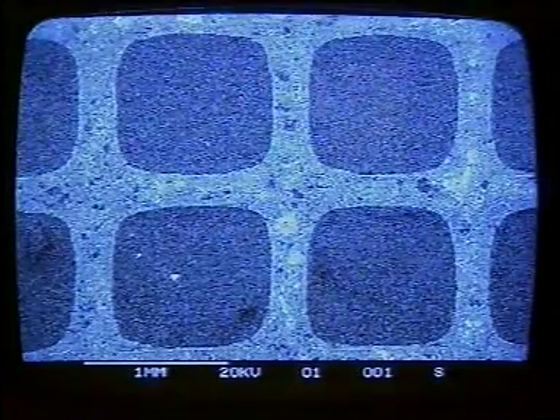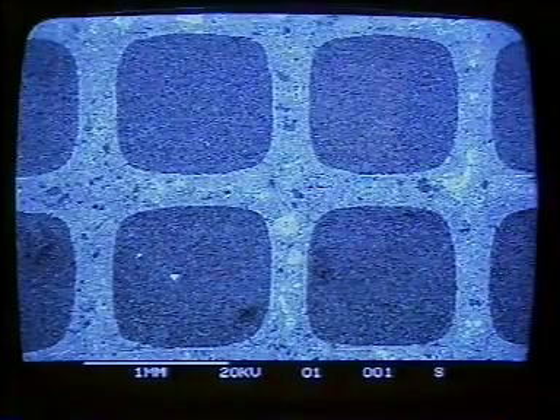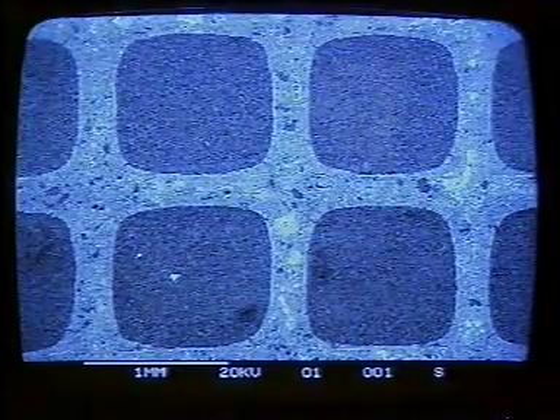As the magnification is increased, you can see that the corners of the channels are rounded. Quite a thick coating known as a wash coat has been applied to the ceramic core. This too is a ceramic material, mainly aluminium oxide and containing some barium oxide. What you see here is a corner of one of the cells. The important thing about the wash coat is that it's highly porous. The pores are tiny, mind you, so you can't make them out at this magnification, but they in effect form a ceramic sponge and increase the surface area by something like 7,000 times. That's the equivalent of the area of 2 football pitches inside each catalyst block.